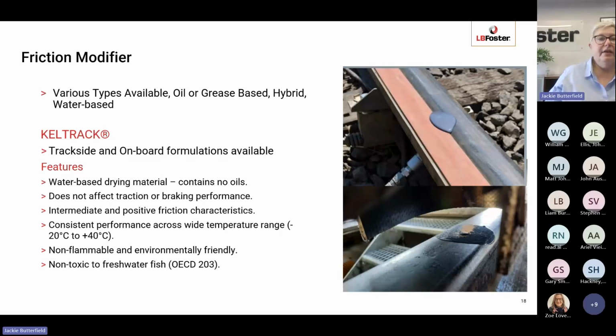So the key characteristic of Keltrack is that it is purely water-based. It contains no oils. So it dries on the rail to form a thin film. It does not affect braking and traction, and we have extensive braking trial data to prove that. It provides an intermediate friction level, so between 0.3 and 0.4, and it has positive friction characteristics. I'm not going to go into positive friction characteristics at the moment because that's very, very key to noise and corrugation, and that's the next couple of webinars. So I'm going to talk a lot more about positive friction in the next couple of webinars.